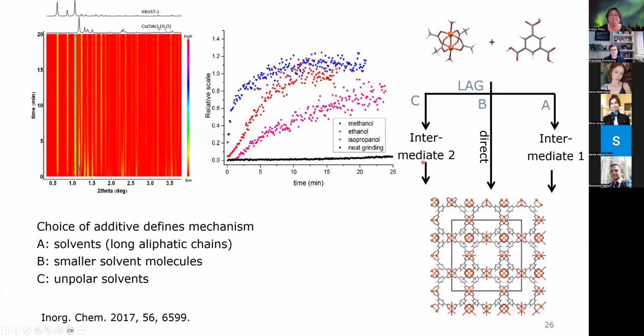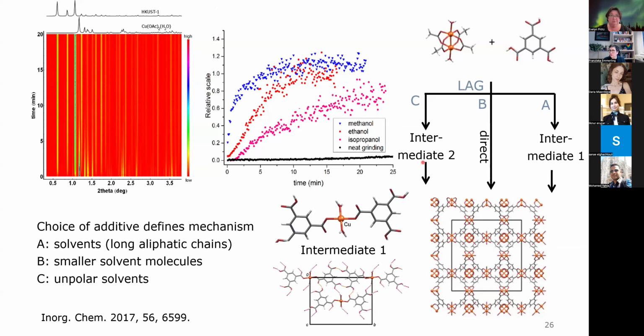And if you investigate these mechanochemical reactions, then you know when to check for an intermediate. You can stop your reaction, perform an X-ray diffraction pattern for instance in the lab, and then we can also solve the crystal structure, which was interesting in that case because the paddle wheel we know from starting materials like the copper acetate and also from HKUST-1 is somehow broken for the sake of this intermediate, which is then reacting to the final compound.